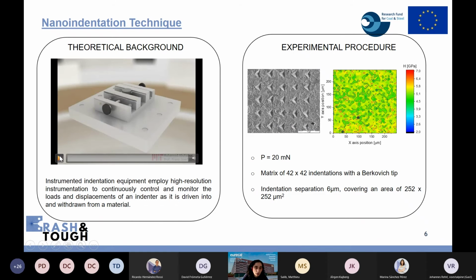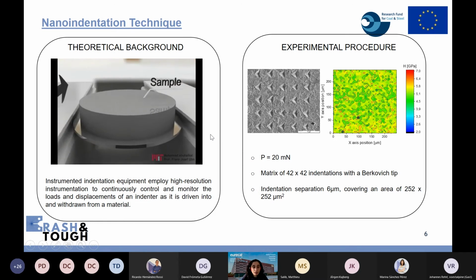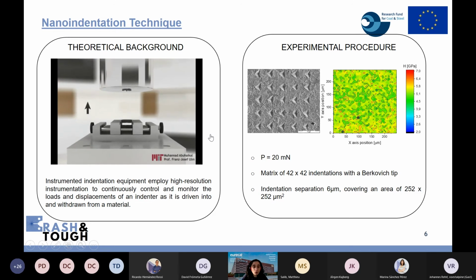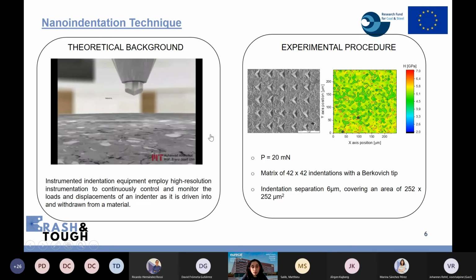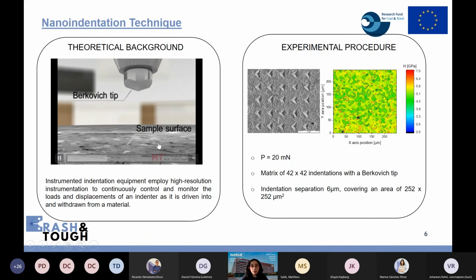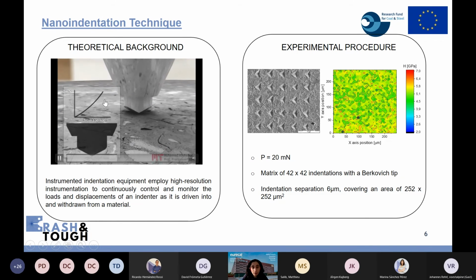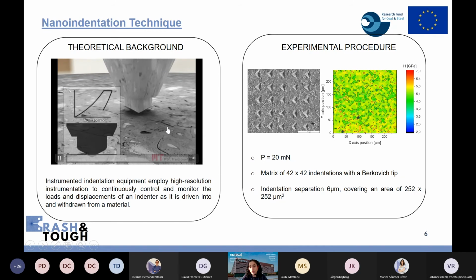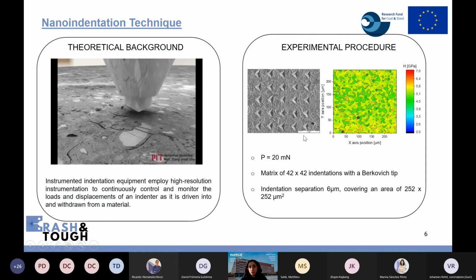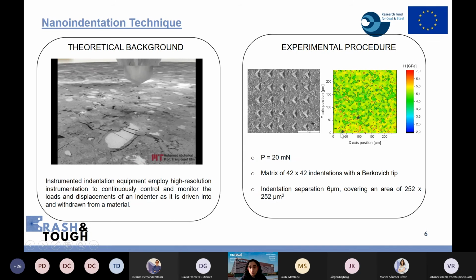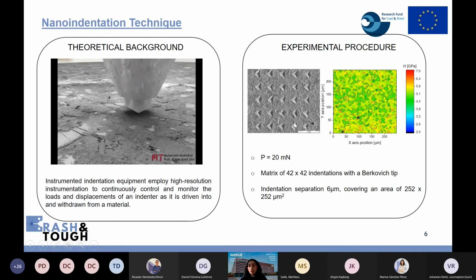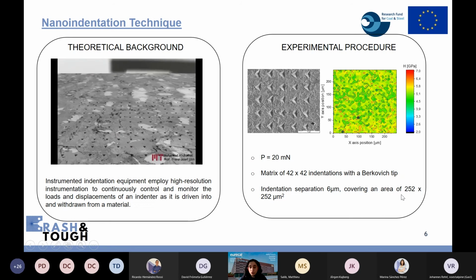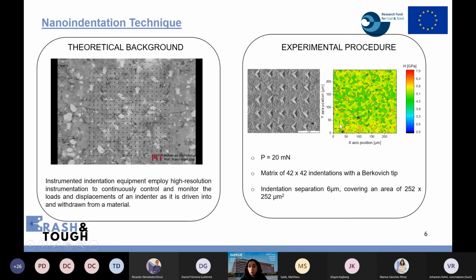So, nano indentation technique, here we have a video. It's an instrumented technique that continuously controls and monitors the loads and displacements of an indenter as it is driving into a material. We can obtain the load and displacement curve, and with that curve and contact mechanics, we can compute hardness and elastic modulus mostly. We have done an array of 42 by 42 indentations. So we have a matrix done in the steels covering an area of about 200 microns. And we can obtain with this technique a mapping of hardness. So we can see the distribution of hardness and this can be related with the microstructure.